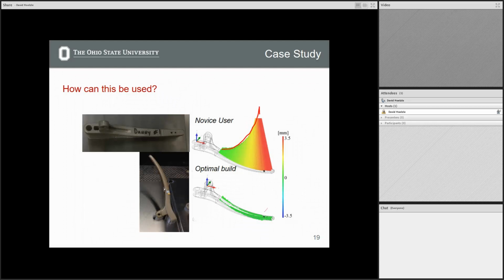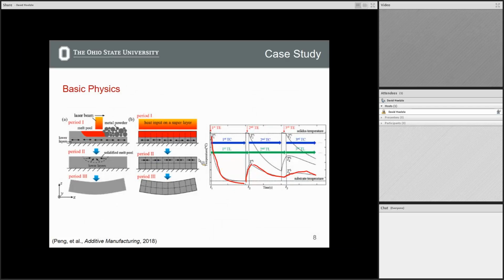In-process annealing, we were not looking at relaxation of residual stress, which is more of a microstructural phenomenon, right? You actually have grain boundaries realigning for that to happen. So we did not have that in there. What I would say, though, is that to make this happen quickly, we're masking a lot of what's going on at the melt pool level. Going back, this is what we were calling super layers as opposed to a single layer. So we're lumping a lot of things that would happen at very high residual stresses at the melt pool into a larger structure, and then that larger structure is freezing as opposed to all these little micro welds. That's not really a scientific answer to your question, but we're essentially muting out a lot of the effects that need to be annealed away by making larger scale structures.